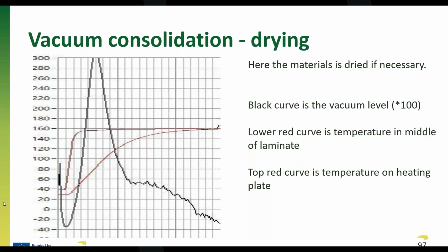But the very important thing here is actually the black one. The black is the vacuum level, and you see the vacuum level goes up and actually down here very much, because here you are boiling off the water. So you see how long time it actually takes for the water to boil off. It's like 2 hours on this one. This laminate was 32 millimeters thick, so it really was taking a lot up. But you see how much the vacuum curve actually changes. So it is very important on this material to do the drying up front. Next one, please.